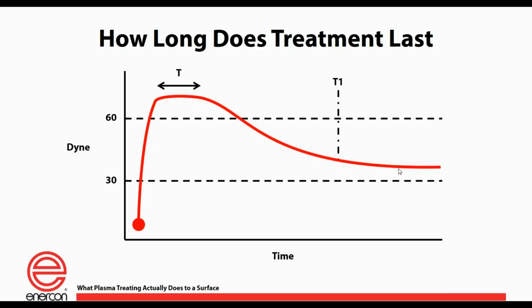I have T1 out there. So let's say that I have done some tests and I need to be above 40 dyne in order to get a good bond for my surface. In this case, I need to figure out what T1 is. So I get up to 60 something, and I've run the trials, and I know that above 40 I get good bond or I get good adhesion. So that's what T1 is.